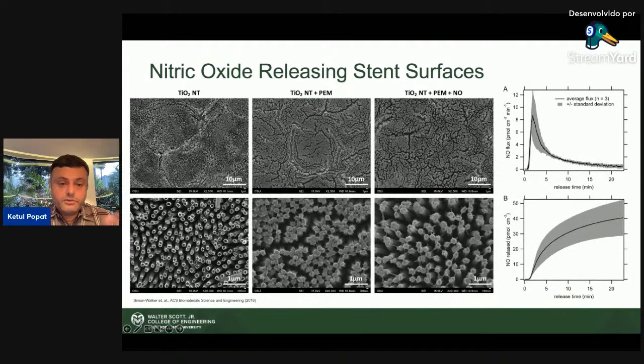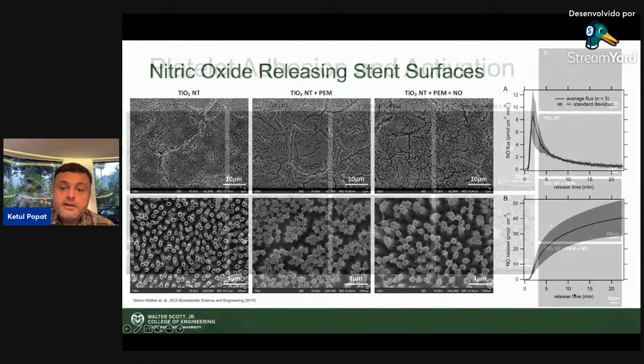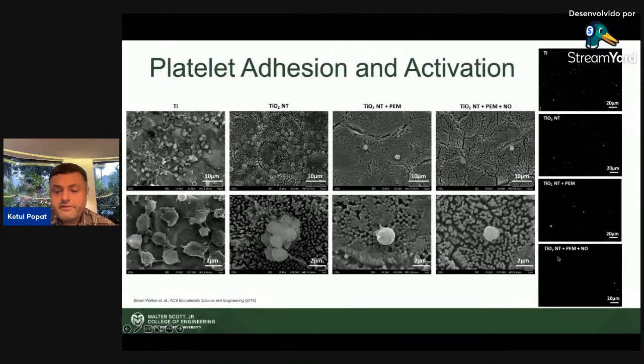You can see that when we do this method, we can still see the nanotubes. We are not blocking all the nanotubes here. And then you can see that you have this release of nitric oxide that happens. Nitric oxide comes very quickly. We don't want this. We want nitric oxide to come for many, many hours. But this was the first step that we wanted to make sure and see how the nitric oxide is actually coming. And the most interesting part was that when we had nitric oxide, we practically removed any blood clotting.